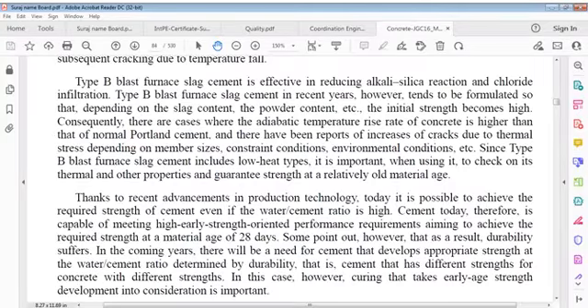Temperature on concrete. Hydration reaction in early ages is activated as placing temperature of concrete increases, although inactive hydration reaction increases with temperature rise ratio in concrete. Adiabatic temperature rise decreases. So this figure shows adiabatic temperature rise according to concrete mix and placing temperature. The temperature rising ratio with placing temperature 35 degrees in a day was higher than that of a specimen with placing temperature 25 degrees.